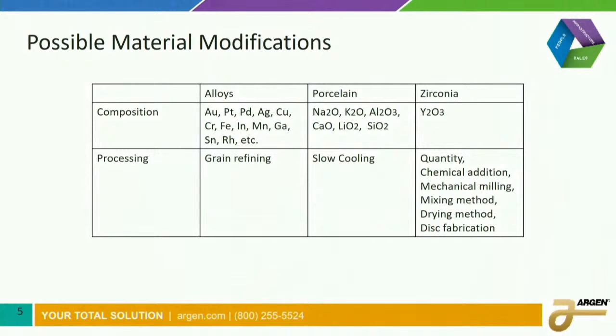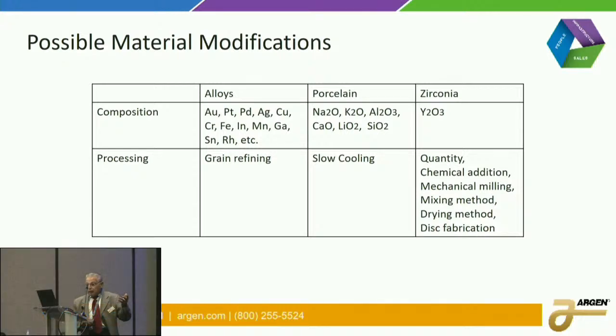In the case of an alloy, if I wanted to make the thermal expansion lower, I add a little platinum. If I want to increase the strength, I could add some tin or indium or manganese. Or in the case of porcelain, if I wanted to change the thermal expansion, I change the ratio of the soda with the potash here. You can't do much with processing on alloys or porcelain, which actually enables you to have a very stable product.